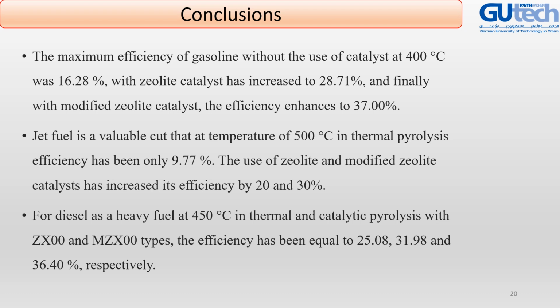Jet fuel is one of the most valuable cuts in this product. At a temperature of 500 degrees Celsius, in thermal pyrolysis, the efficiency is only 9.77, while for the zeolite and modified zeolite catalyst, it has increased to 20 and 30%. And finally, for the diesel as a heavy fuel at 450 degrees Celsius, in thermal and catalytic pyrolysis with zeolite and modified zeolite, we produce 25, 31.98 and 36.4 respectively, which is for the modified zeolite.